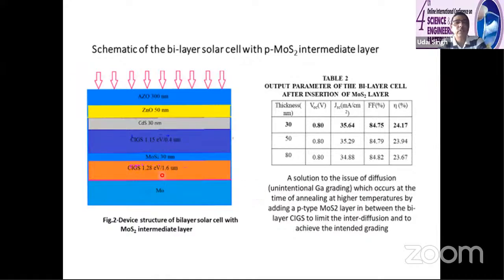So what we have proposed is moly, then you have a CIGS layer, which has around 1.28. The total thickness of CIGS we want is around 2 micron, so we have divided this and optimized it. On the top layer, 1.15 electron volt with thickness around 0.4 micron, and this is 1.6 micron. If you don't use any interfacial layer, there is a possibility during the high temperature process of some interdiffusion, and then you cannot maintain this stoichiometry.